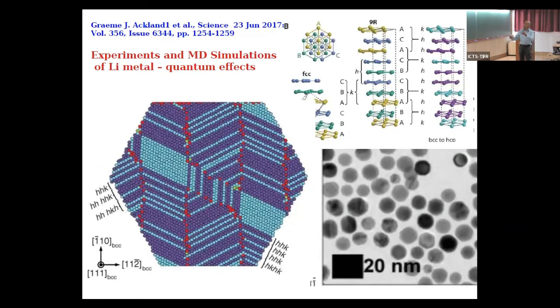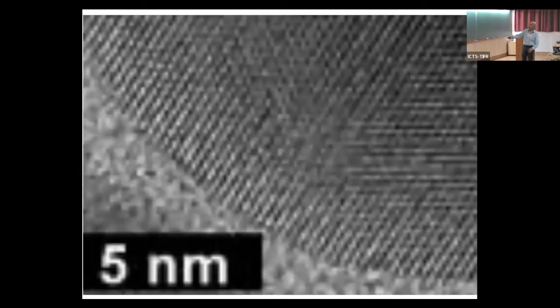So if you look at simulations that are available about gold nanoparticles, you find lots of faults. Thapa and Pandey have created this situation because now in fact there are electron microscope images which I have analyzed, and if you look at them, I can find many stacking faults. So to me, they are sources of local pairing because of the two-dimensional, one-dimensional physics.